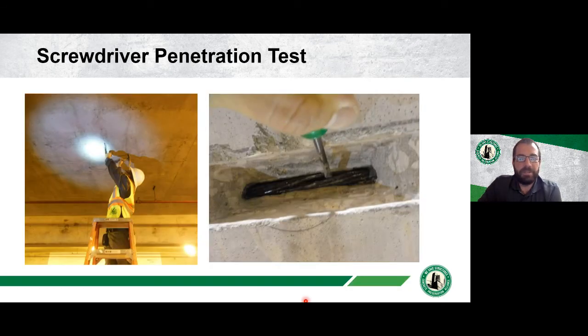Another test that we can do is do some openings and then check to see if the tendon is still under tension. If you can fit a flat blade screwdriver between the individual wires of the strand, then that's an indication that the strand is no longer under tension, and that's called the screwdriver penetration test.